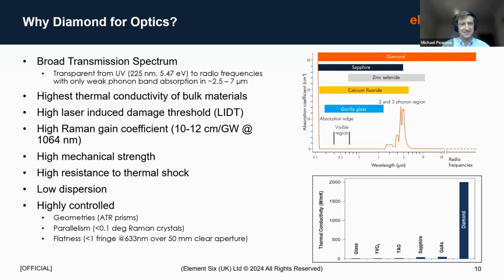They don't look as impressive or as pretty, perhaps, as a round brilliant cut diamond for jewelry, but the tolerances that you work to on these prisms are much higher than for any gemstone. Also, things like parallelism and flatness. On parallelism on our Raman crystals, we achieve less than 0.1 of a degree on the parallel end faces through which the laser will pass. And routinely we achieve flatness on large diamond optics, so 50 millimeter diameter optics, of less than 1 fringe at 633 nanometers. So we're able to achieve very high flatnesses over large area parts.